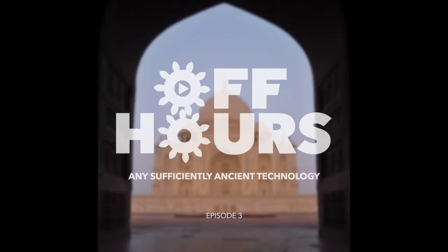One of the inventions of the 20th century, I guess, in terms of casting technology was the use of vulcanized rubber for making a mold of something that you've made. You would make a wax original, a master, cast it in metal, clean up the metal, polish it, and do everything you need to do with it. And then you would surround it in rubber, heat that rubber up and vulcanize it. So you would then create a perfect rubber mold around this metal original.